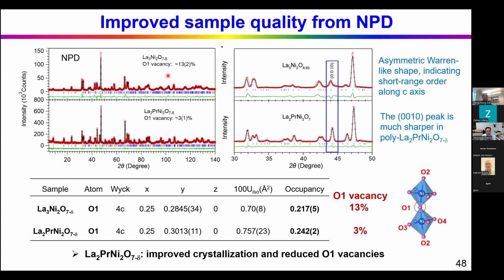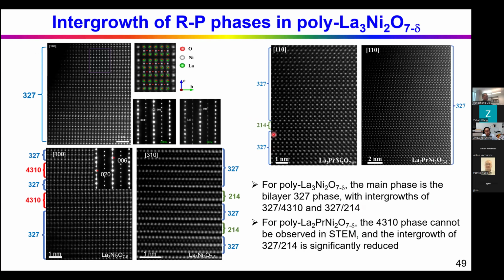And from the refinement, we also refined the oxygen occupancy of the O1 site. We found indeed for this undoped sample, there's some vacancy. But for this doped sample, it's nearly fully occupied. So from this neutron diffraction, we indeed show that the doped sample has a better quality and negligible oxygen vacancy. And we also used the TEM to further confirm this result.